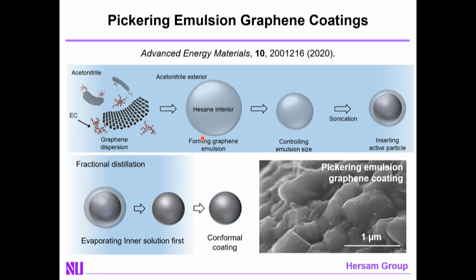Well, it turns out that the particles we're trying to coat, namely the lithium metal oxide particles, disperse selectively in hexane compared to acetonitrile. And as a result, if I add the particles to that emulsion, they will be recruited to the interior of the droplets. By tuning the emulsion size to be just bigger than the particles, which can be done by the ratio of the two solvents, you can now have a situation where you have one and only one particle inside of each droplet. And remember, on the surface of the droplet, you have the graphene that you want to use to coat the particle.